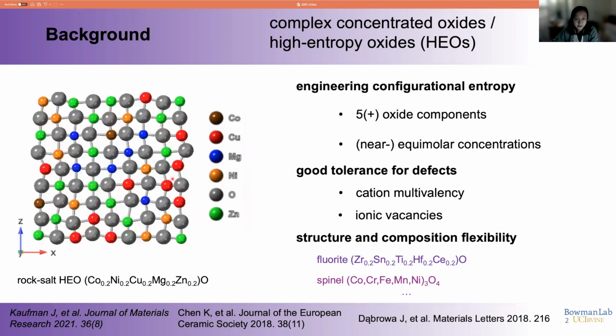Like this schematic shows, in this plan view, each cation has a different radius. Also, they may have different valence states, but they still stay in the same rock salt phase. So high configurational entropy offers HEOs good tolerance for cation multivalency and ionic vacancies.